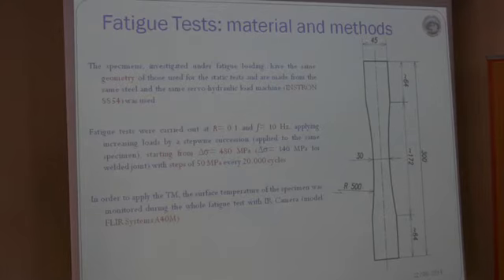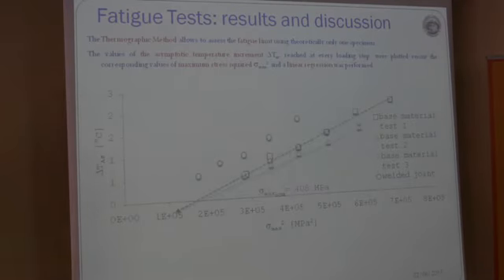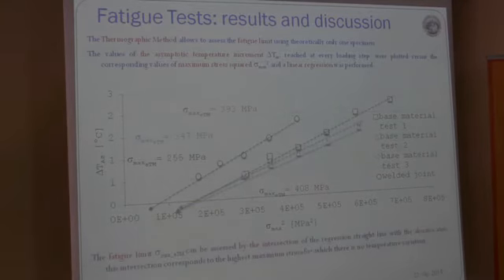After, we made the fatigue test with the same geometry and the same material, with a loading ratio of 0.1 and a frequency of 10 Hz, and we used, of course, the IR camera for the thermographic methodology. And we plot the temperature increment versus the square of the maximum stress, and we look for the fatigue limit where the increment of the temperature is 0.